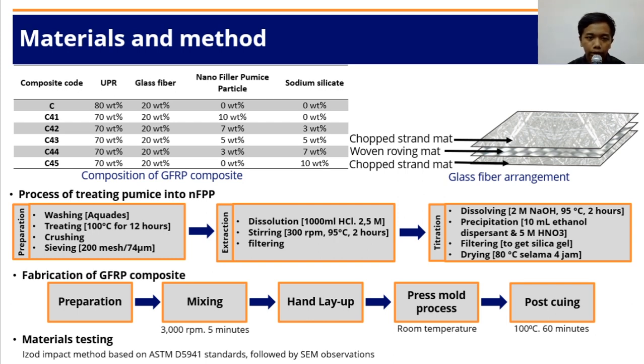In the extraction process, 100 grams of pumice particles were dissolved in 1000 milliliters of 2.5 molar hydrochloric acid and stirred with a magnetic stirrer at 300 rpm at 95 degrees Celsius for 2 hours to separate the silica-rich pumice particles. In the titration process, the particles were washed with distilled water until they reached a pH of 7. The sodium silicate solution was prepared by dissolving 10% of silica-rich pumice particles in 2 molar sodium hydroxide at 95 degrees Celsius for 2 hours.